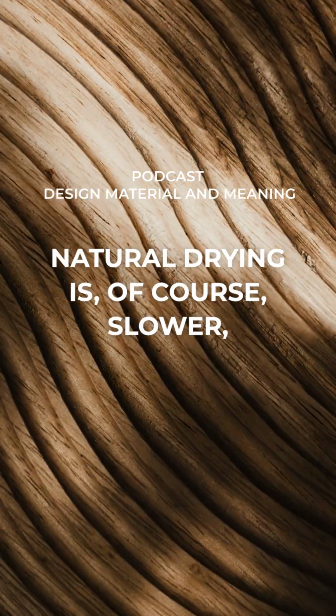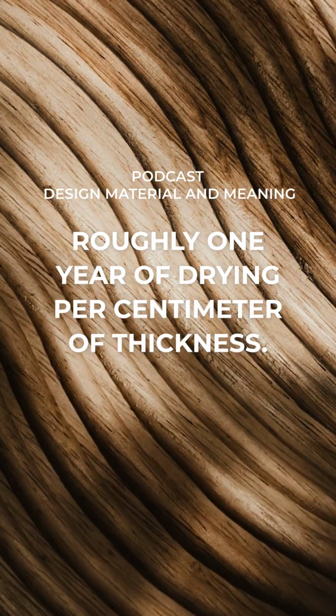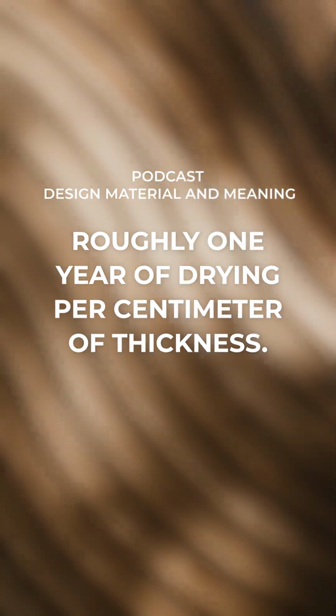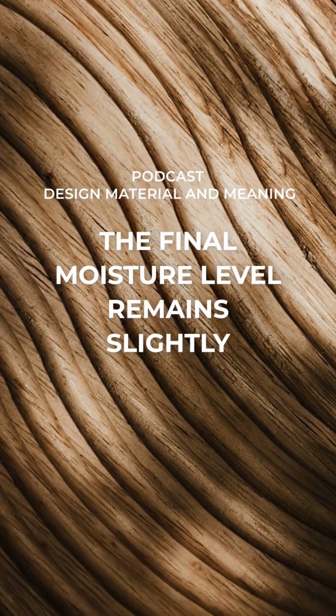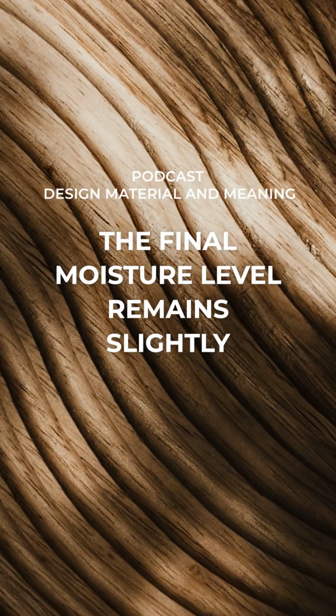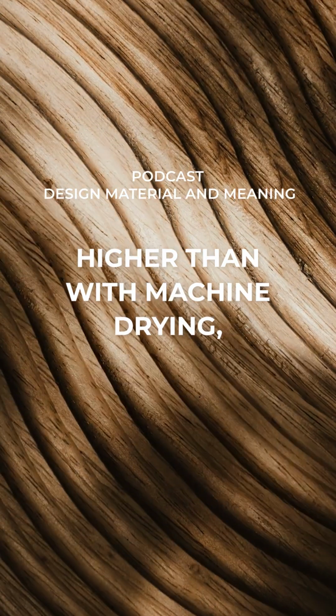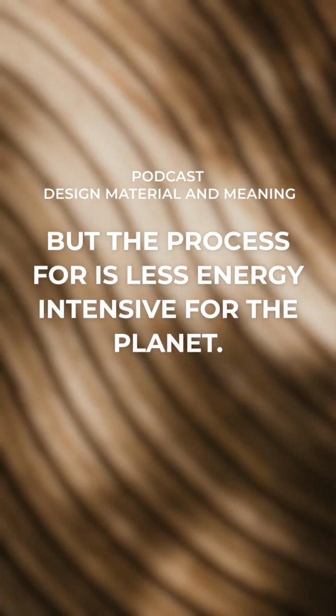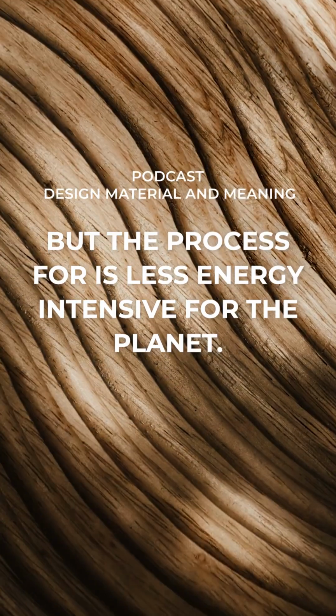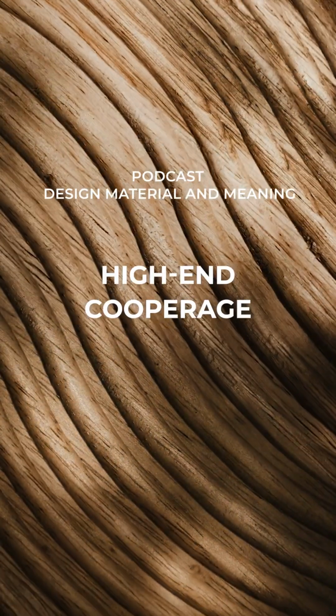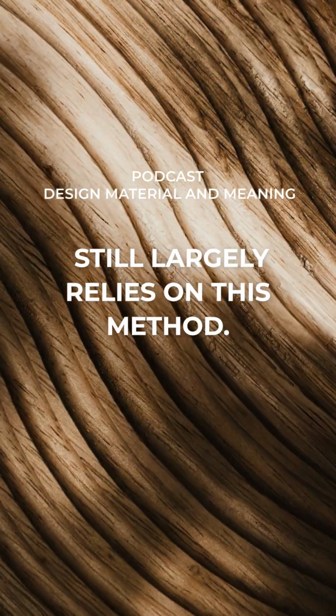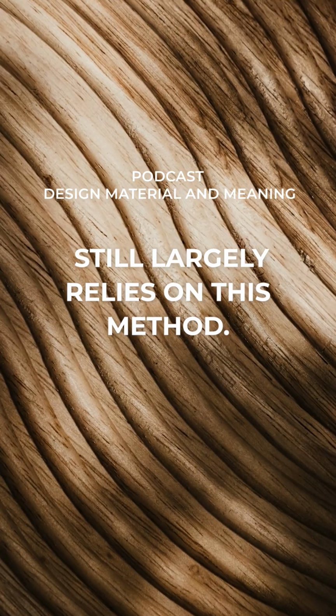Natural drying is, of course, slower, roughly 1 year of drying per centimeter of thickness. The final moisture level remains slightly higher than with machine drying, but the process is much less energy intensive for the planet. High-end cooperage still largely relies on this method.